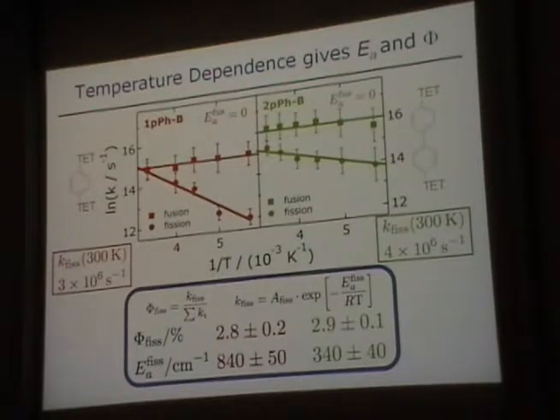And the reason the answer is no is because the fission rate, the rate of splitting into two triplets, is very small, on the order of 10 to the 6 inverse seconds, I guess, 10 to the 6 hertz. So a microsecond. It takes them roughly a microsecond to split apart. But tetracene's decaying in 20 nanoseconds. That's the singlet lifetime, right? So you barely get any triplet pairs out before the singlet states decay away. So our yields are low, a couple percent.